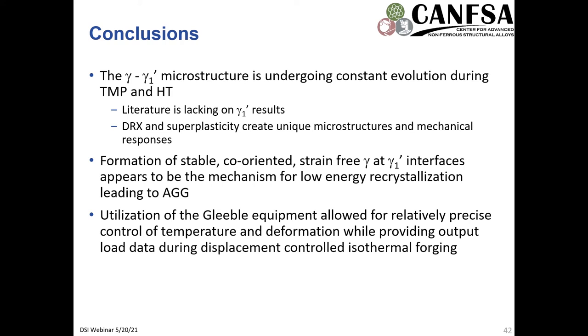And dynamic recrystallization and superplasticity during the isothermal forging create a unique microstructure and interesting mechanical responses at different strain rates and temperatures, perhaps the inverse of what we may initially think. And the formation of the stable, co-oriented and strain-free gamma shell at these primary gamma prime interfaces appears to be the mechanism for a lower energy barrier to recrystallization that leads to abnormal grain growth, because we're having very few nucleation sites occurring.